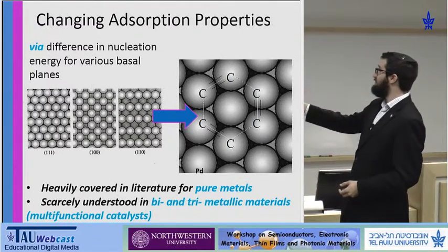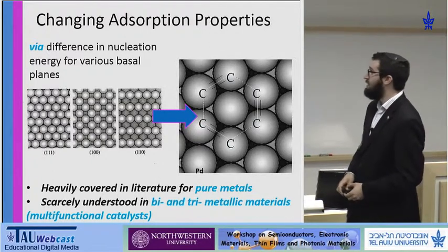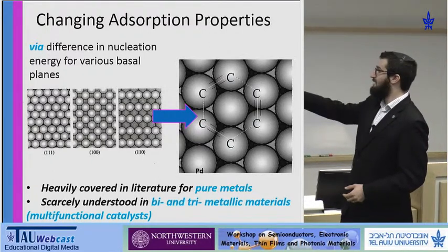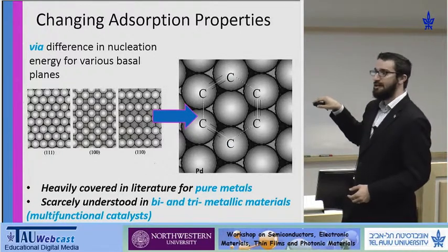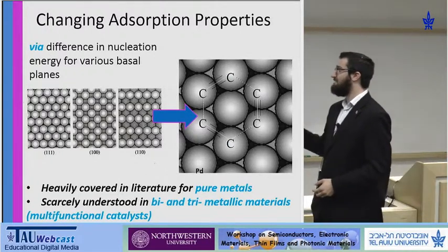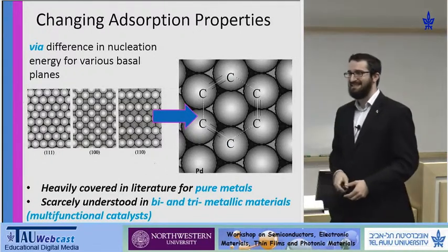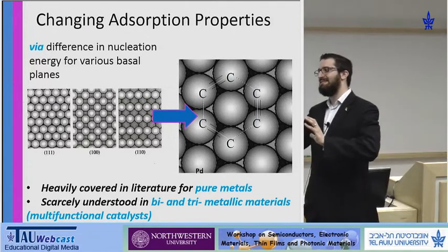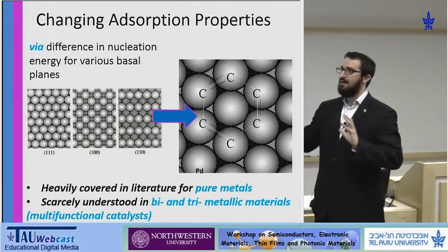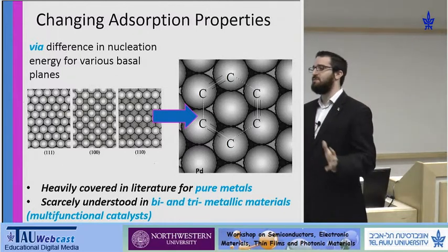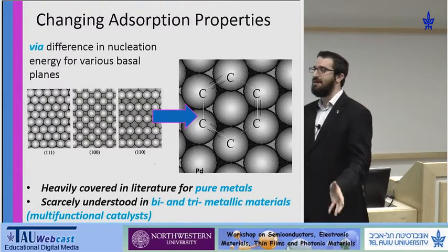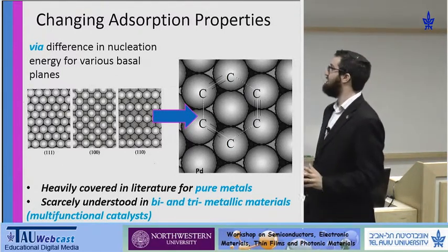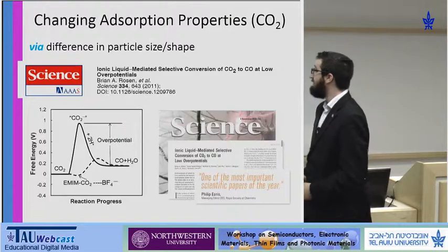I'll remind you also of the benzene example, where if we're changing the crystallographic orientation by pulse plating or other techniques, we're effectively changing interatomic bond distances. And if we tune the bond distances right, it can either inhibit or enhance the adsorption of relevant molecules, namely hydroxide and oxygen in the case of oxygen reduction.